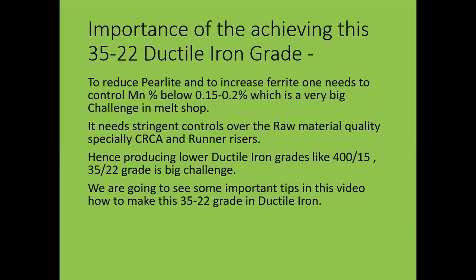It needs stringent controls over raw material quality, especially CRCA and runners. Hence, producing lower ductile iron grades like 400 by 15, 400 by 12, 35 by 22 are big challenges. We are going to see some important tips in this video on how to make 35 by 22 grade in ductile iron.